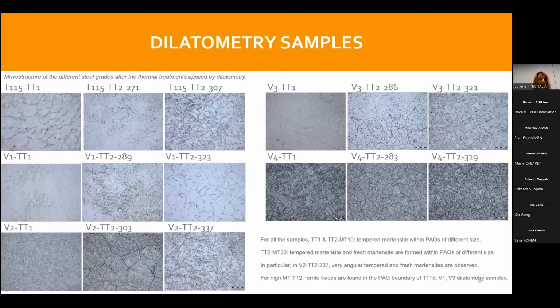Let's see the microstructure of the different steel grades after the thermal treatments have been applied by dilatometry. The first picture corresponds to the result of the application of the standard thermal treatment to each steel grade. And then the second and the third pictures correspond to the result of the application of the innovative thermal treatment 2 with MT10 temperature and with MT30 temperature.